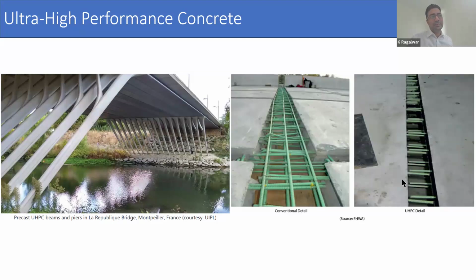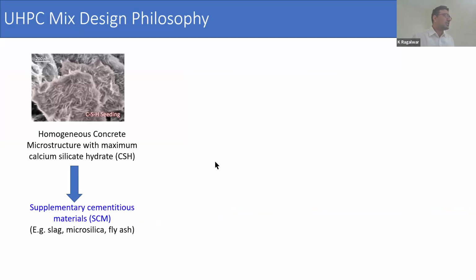Not only that, with 21 ksi or 150 megapascal strength of concrete at 28 days, it can achieve very high strength within 7 days. So this kind of detail is also used in accelerated bridge construction, where you bring in precast members and connect them on site, and within 7 days, the traffic can be opened rather than waiting for longer times. So with that, we'll briefly discuss UHPC mix design philosophy.